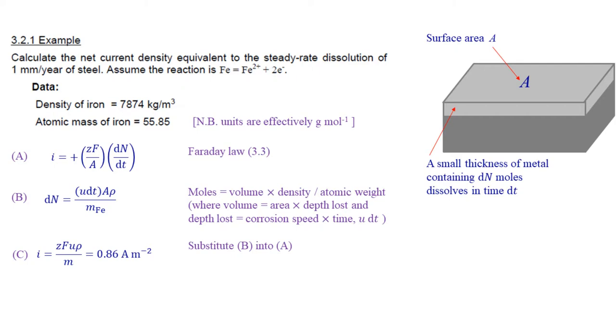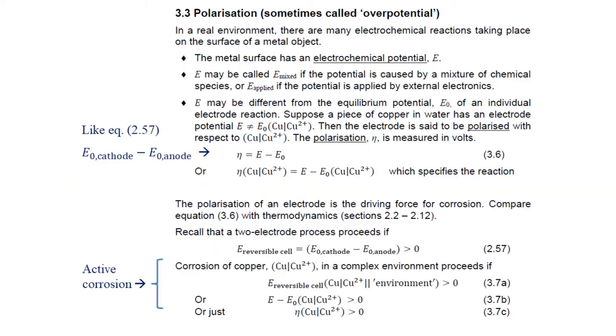That's a number worth knowing roughly, because for many metals, a uniform corrosion speed of 1 millimeter per year will be roughly in the order of magnitude the same corrosion current density as this. So roughly somewhere around 1 amp per meter squared. Now, in a real situation, there is not just one process making up the net current density affecting a metal surface. There is a mixture of processes, and we need a theory to describe each one of them. Section 3.3 on page 27 outlines how to do this.